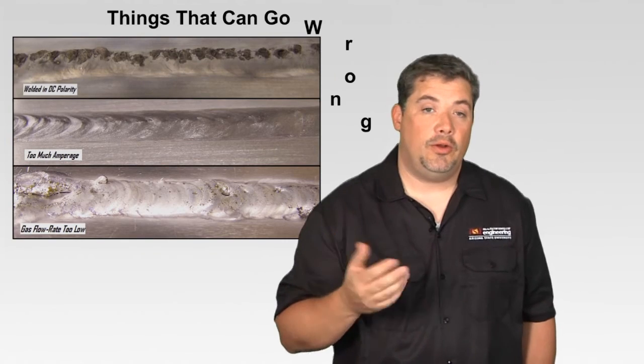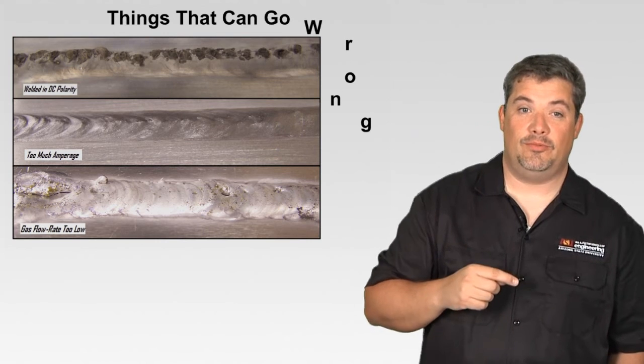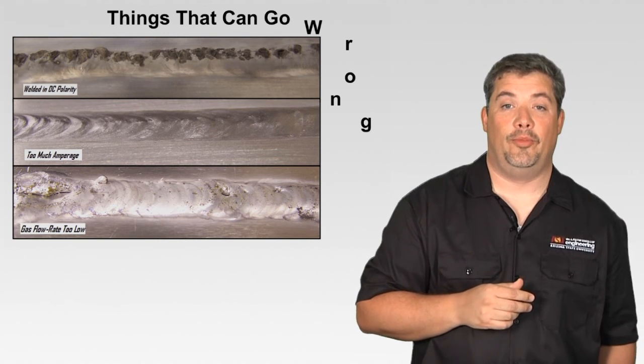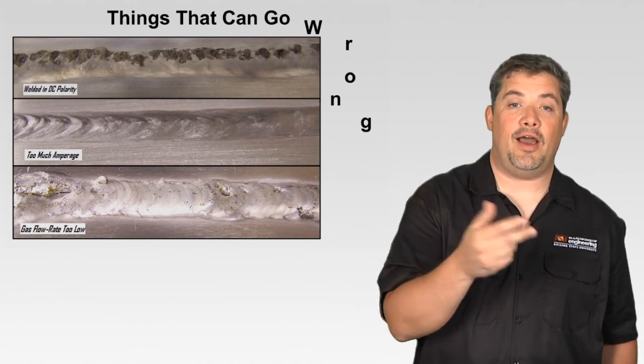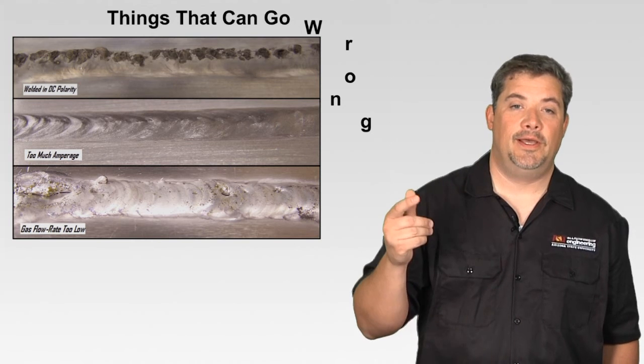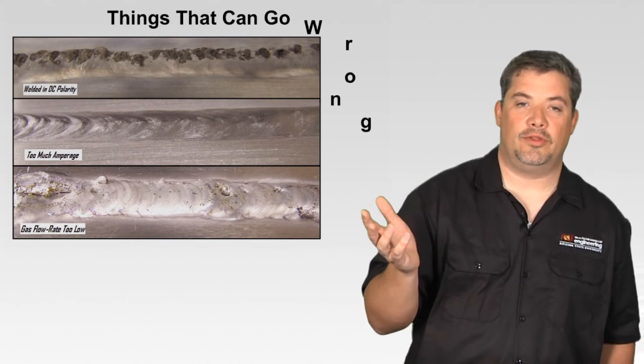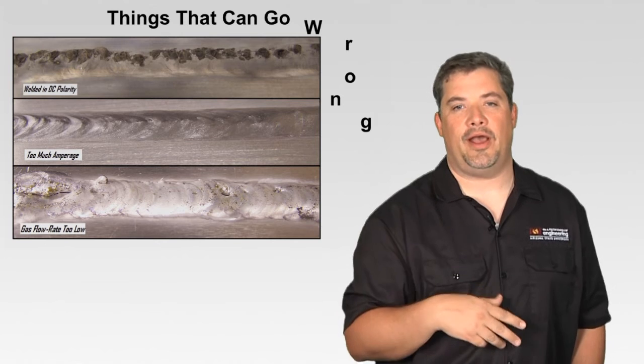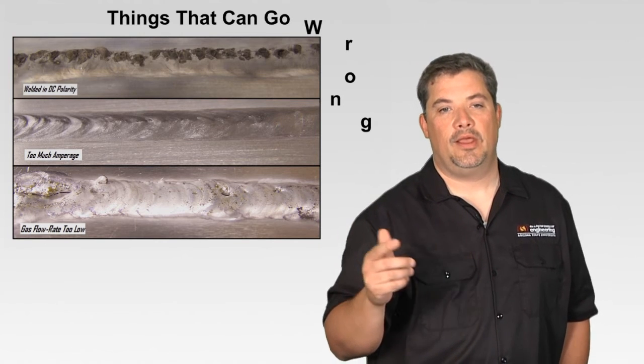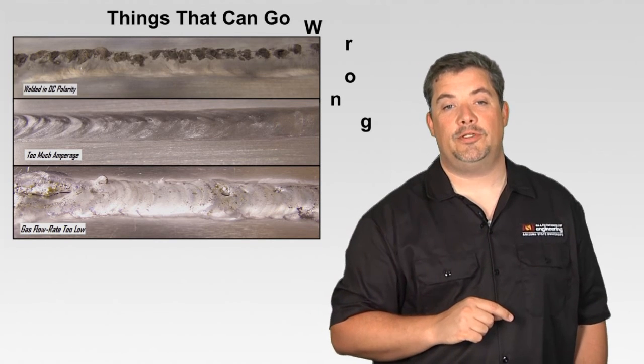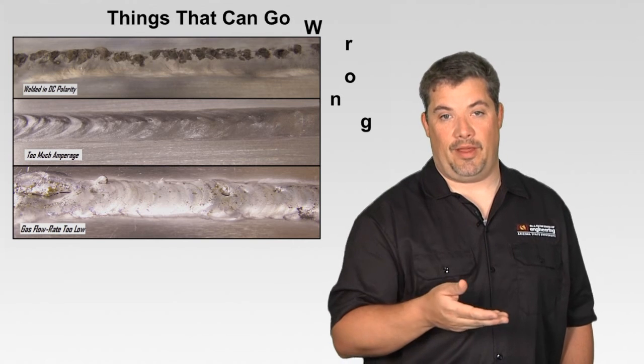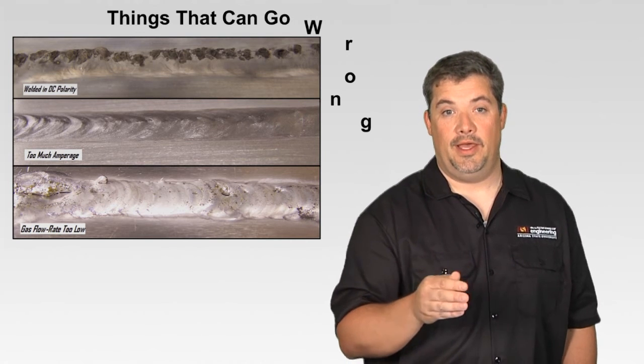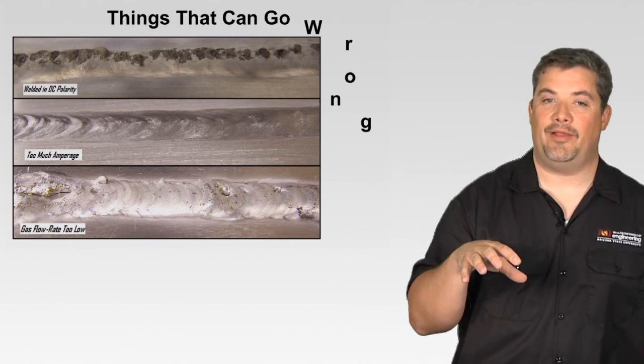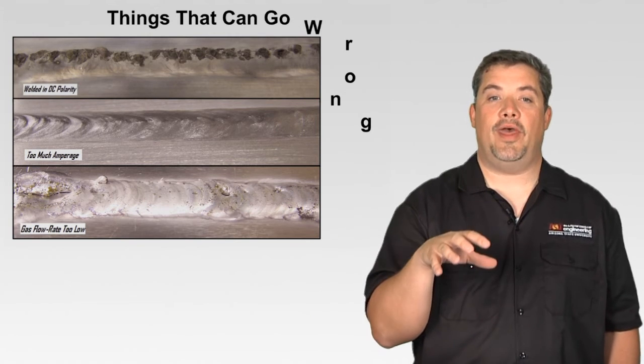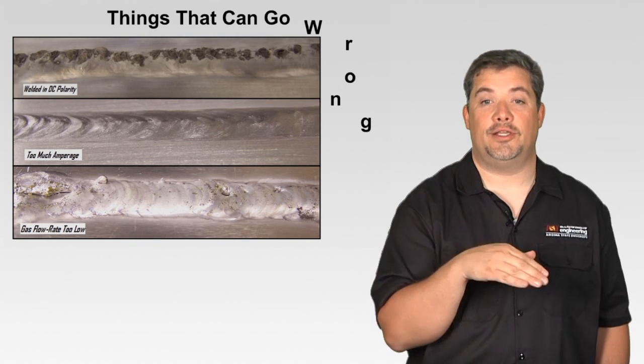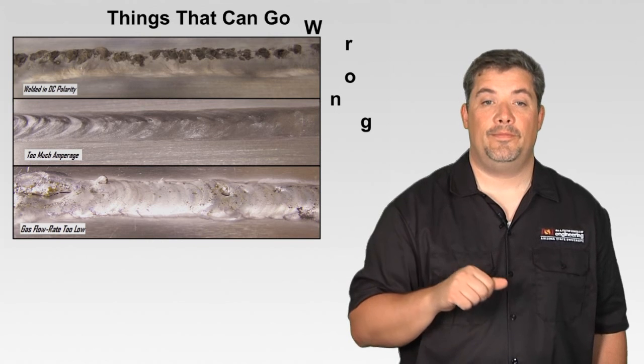So things can go wrong in welding. Well, you can see in some of these images, welding with direct current polarity on aluminum. You can see there's a lot of heavy oxidation on that aluminum surface. It's terrible. Some smoke kind of happening because we're burning off stuff. Bad news. The middle one, you can see there's too much amperage. So you can see the solidification of that puddle is very V-like. So the center is solidifying a lot slower than the edges, therefore potentially causing me cracks down the middle of the weld.